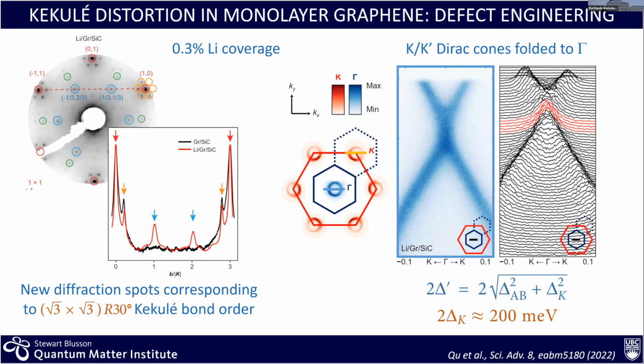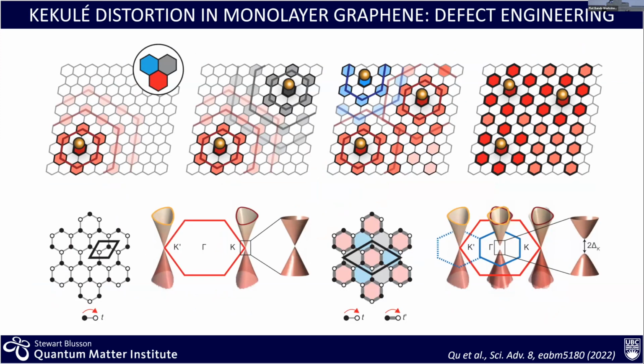You can see in the line cut across all these data points that by putting in a small amount of lithium, nothing really changes. The sharpness of the peak stays the same. What really is the new information is new peaks due to the folding of the structure corresponding to the bond order. Now, the way we understand it is the following. We wanted to establish this particular phase. We come in with the lithium adatom on the surface.